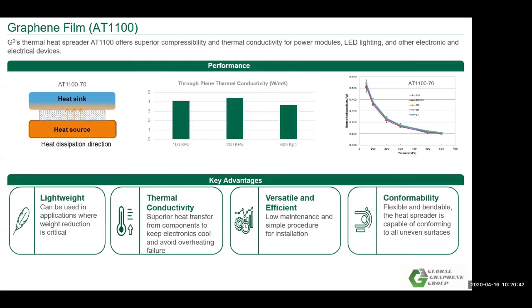In this slide, we just want to show the audience the way to use it from a heat source to the heat sink, under different compressed pressure, and it offers very low thermal resistance. We also did some study on the stability of such film under different circumstances, for example, high temperature, low temperature, temperature shock. This film still maintains intact and keeps the same performance as it is at room temperature.